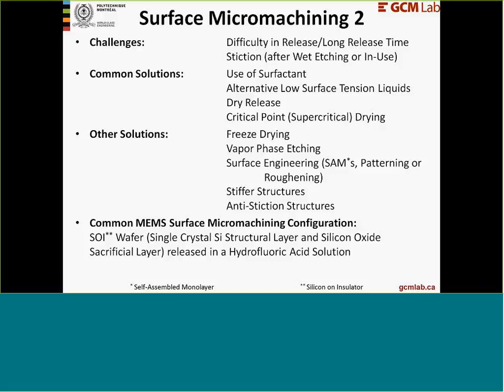There are many solutions to these challenges. The use of a surfactant can facilitate the release of a structure with small release holes. Alternative solvents with lower surface tension can be used to prevent the stiction. Dry release is another way to avoid stiction. Another common technique is critical point drying that takes advantage of the fact that in the supercritical state there is no surface tension. Other solutions that are less common but are still useful are freeze drying, vapor phase etching, surface modification, making the structure stiffer, and finally using anti-stiction structures.